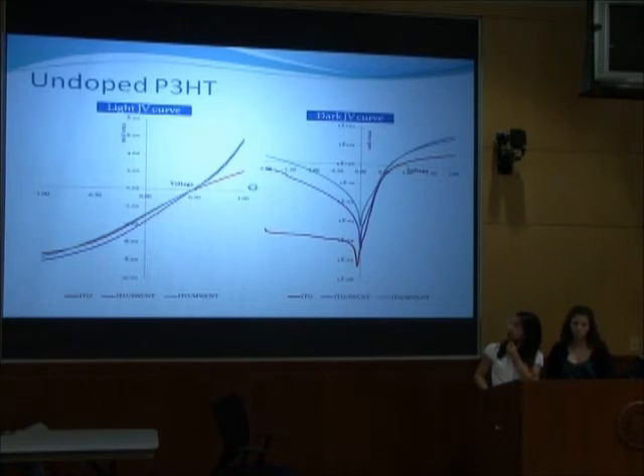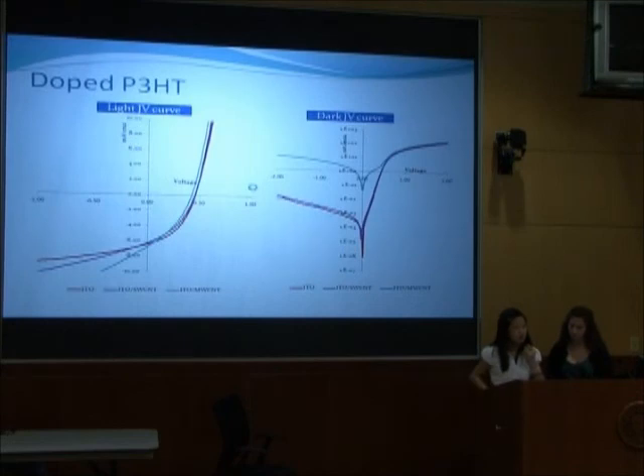This is the device with a P3HT hole transport layer. As you can see, the nanotubes are no longer shorting the device. However, because the P3HT adds about another 150 nanometers of thickness to the solar cell, it increases the resistance, which decreases the amount of power that's generated. Finally, you see our control device with a doped P3HT hole transport layer. As you can see, the nanotube curves are almost identical to the reference curve, and a significant amount of power is being generated, and the efficiency is rather high.